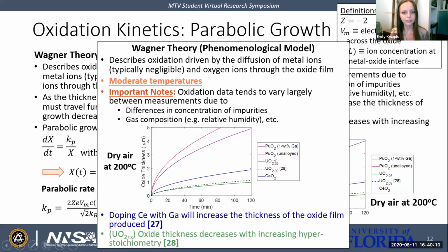You see the general trends where unalloyed plutonium is more reactive than plutonium alloyed with gallium. And you see this difference in the oxide thicknesses between the different hyperstoichiometries of uranium oxide, as you expect to see. I do want to note that oxidation data tends to vary largely between measurements and literature. I'm using diffusion coefficients from literature. That's what I have to work with since I can't run experiments myself.